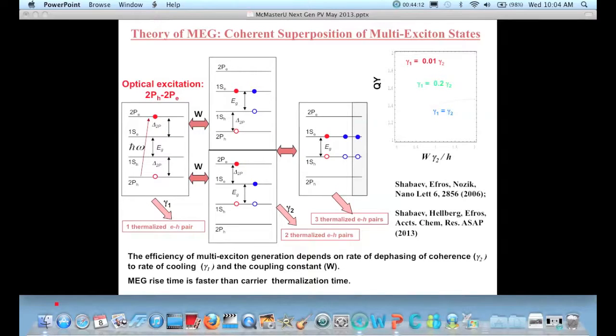So there's 2 excitons. One exciton has an excitation energy of 1 EG. So in all 3 cases, you have, say, 3 excitons with 1 EG, or 1 exciton with 3 EG excitation, or 2 excitons, one of which has 2 EG excitation and the other 1. So they all sum to 3, and therefore you have a coherent superposition. And it's the dephasing which determines how many you get. When you have this asymmetric structure, this dephasing time dominates, it breaks the coherence, and you're left with 2 excitons per photon.